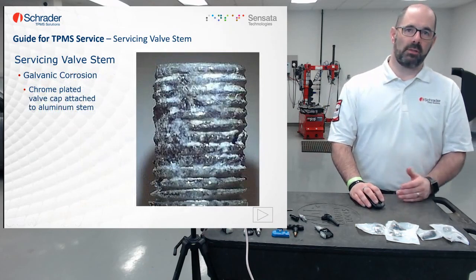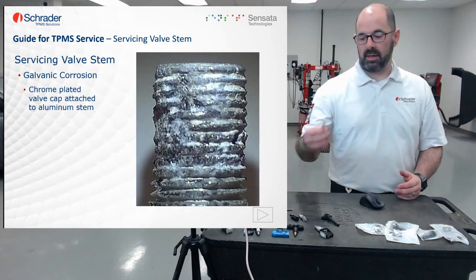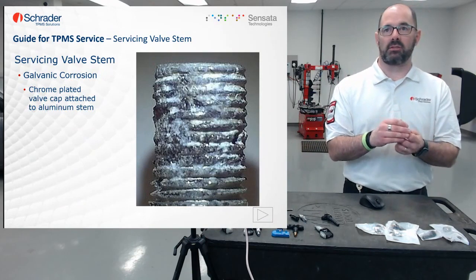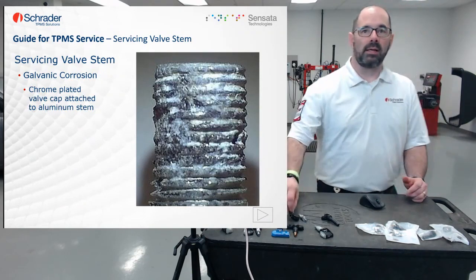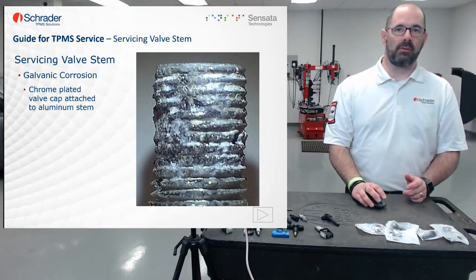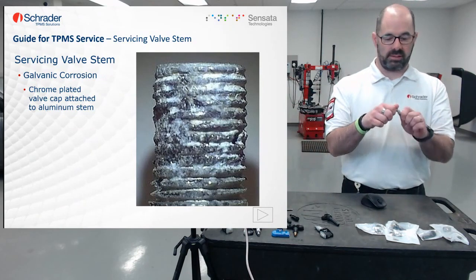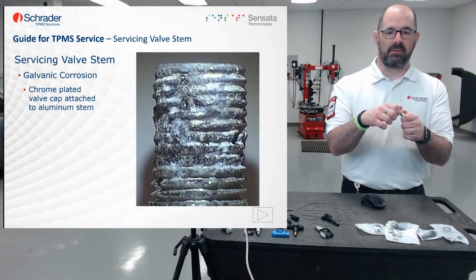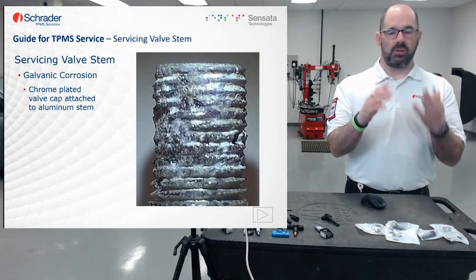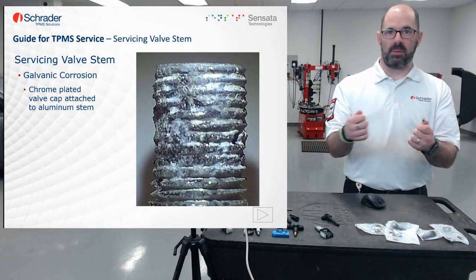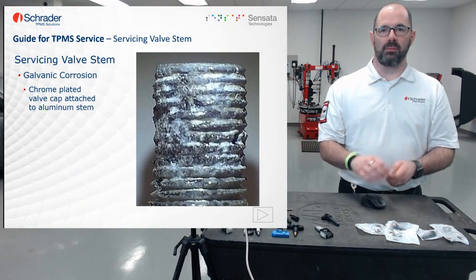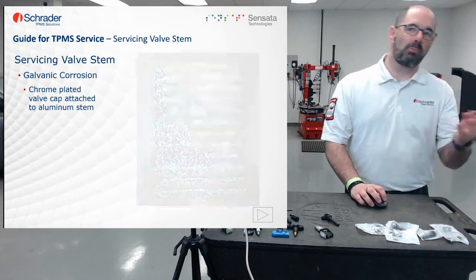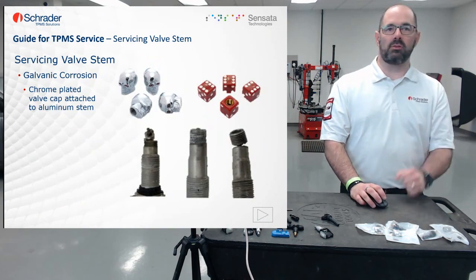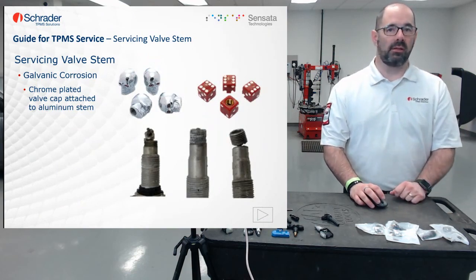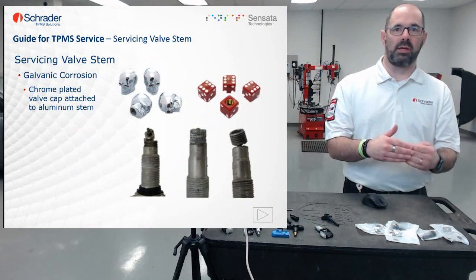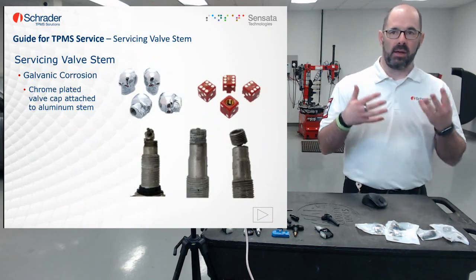So here's our recommendation. As you check the valve to see if there's a sensor attached at the end of it, you can also identify if there's any pre-existing damage to the valve. You'll want to do that 2-finger twist test. If you cannot remove that valve cap with just your 2 fingers, don't go and grab that pair of pliers and rip it out. Instead, go and see your customer and let him know that the chrome-plated cap that he put onto his metal stem has created galvanic corrosion. It created corrosion between the cap and the stem, and now the cap is bonded with the stem.